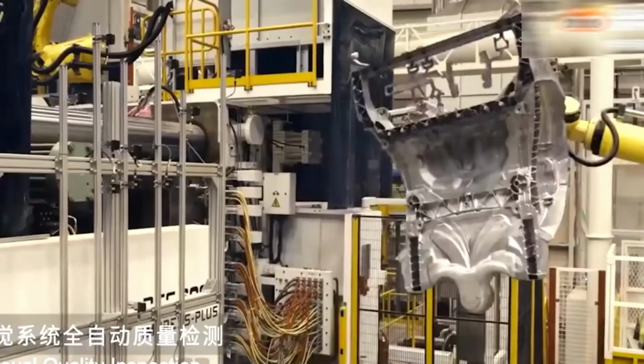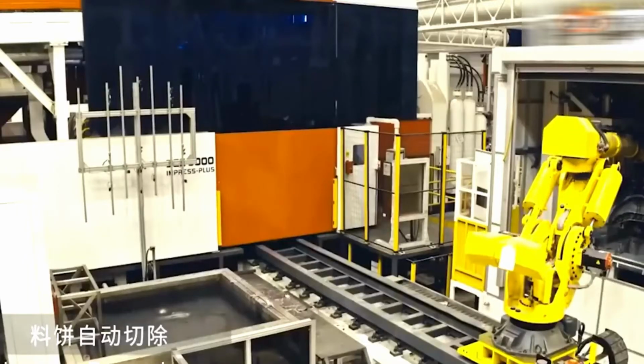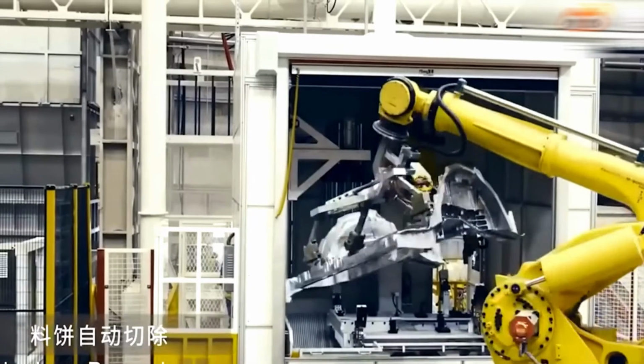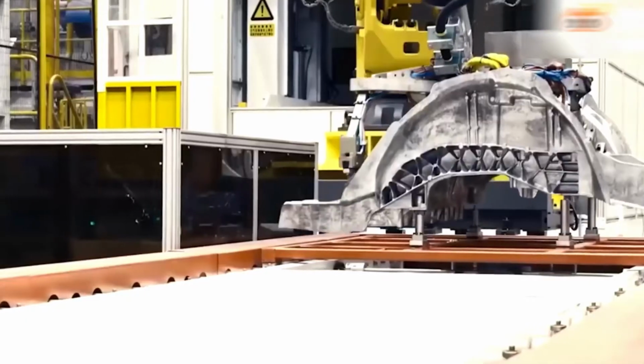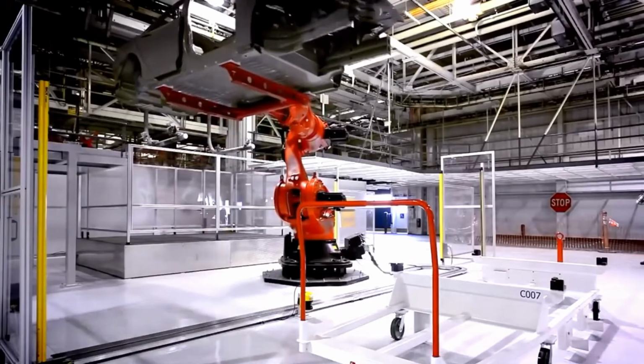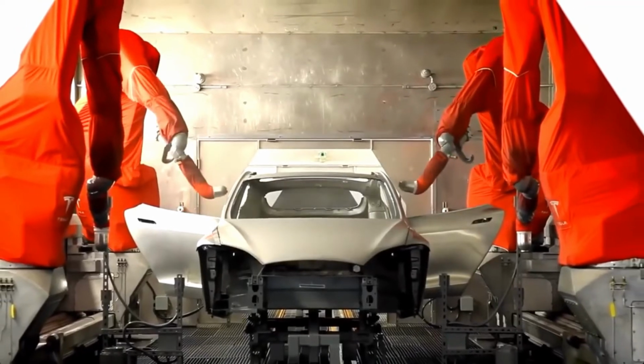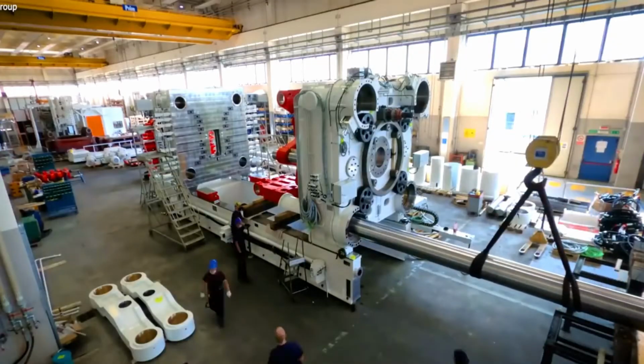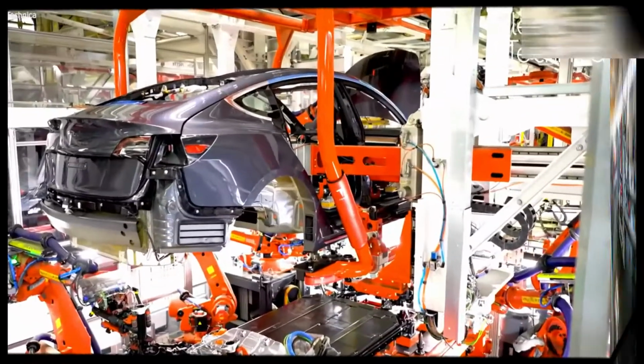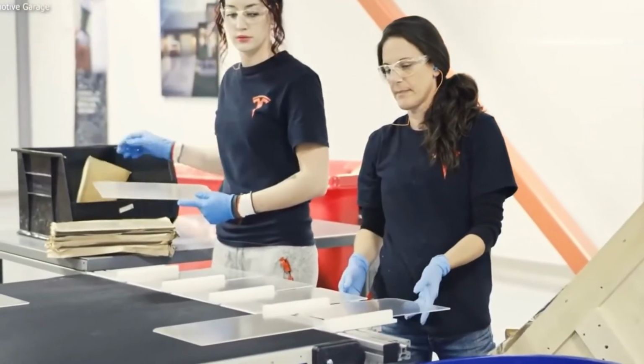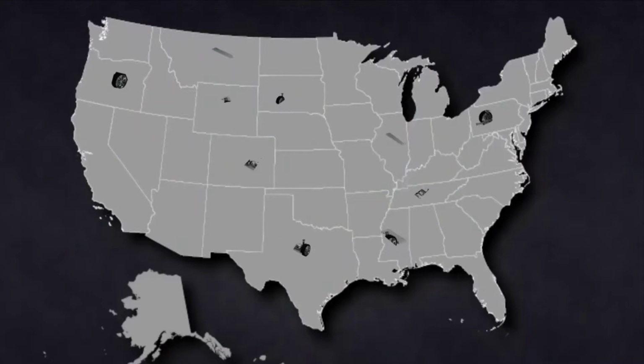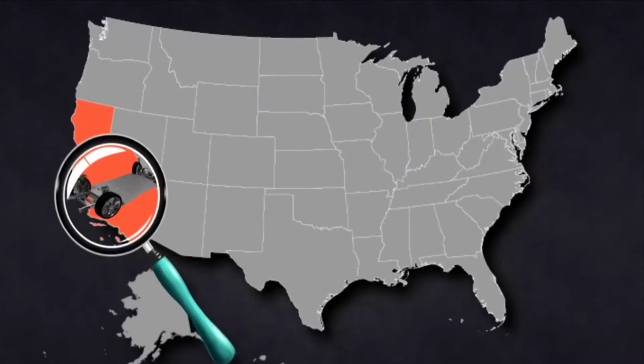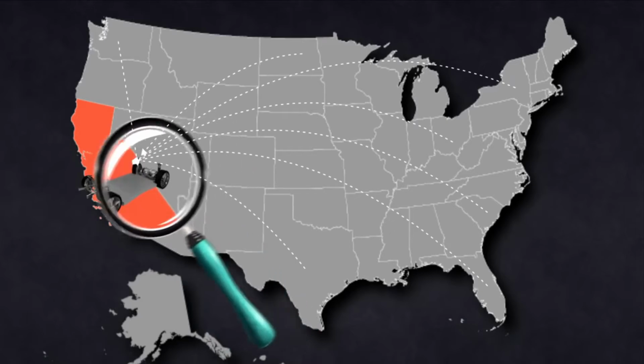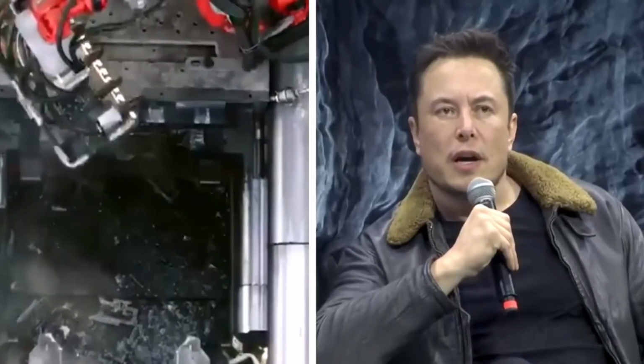At the beginning of each casting cycle, robots spray 35 milliliters of soybean oil in a thin layer inside each half of the mold to allow separation. The mold is closed and a low vacuum of 50 millibars is created by pumping out the air from inside. A precise amount of molten metal is pumped from the holding oven into the casting chamber of the GigaPress at 750 degrees Celsius and forced into the mold using a high-speed plunger with an additional 8 milliliters of lubricant. The mold is opened and the raw casting removed at 400 degrees Celsius.